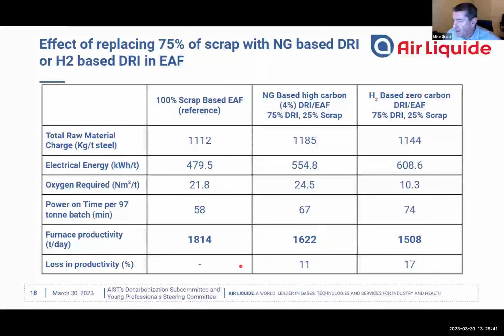And here's an example of some calculations that were done for melting steel to make steel in the electric arc furnace. The reference, of course, is 100% scrap. And you can see this is not a model furnace. It's a rather unimpressive performance, but 480 kilowatt hours per ton is not so uncommon. And 22 normal cubic meters of oxygen.